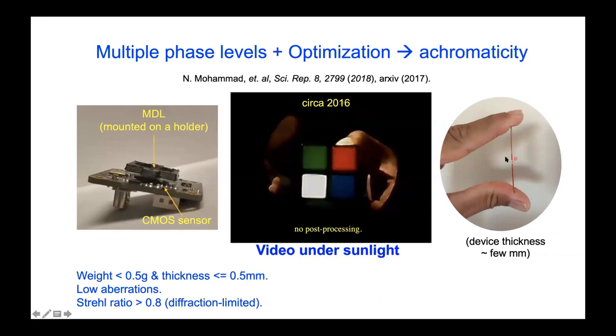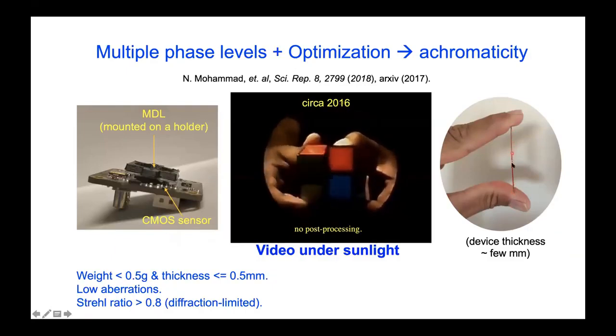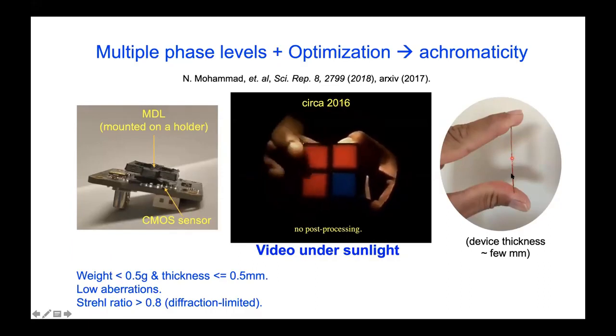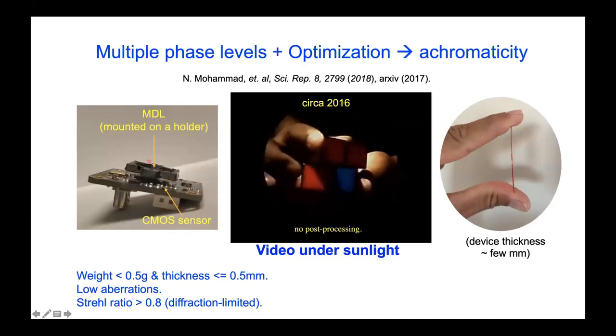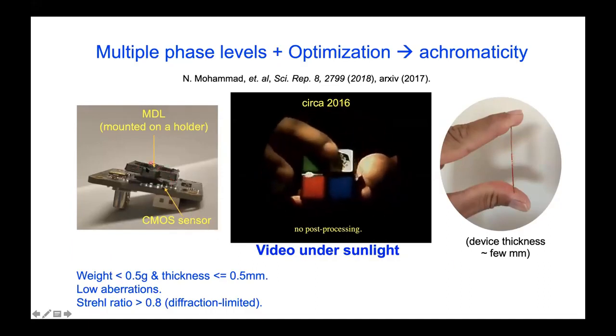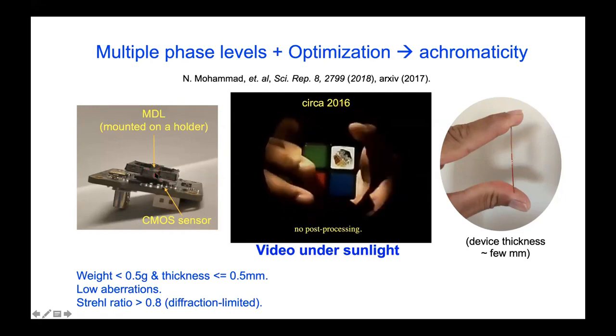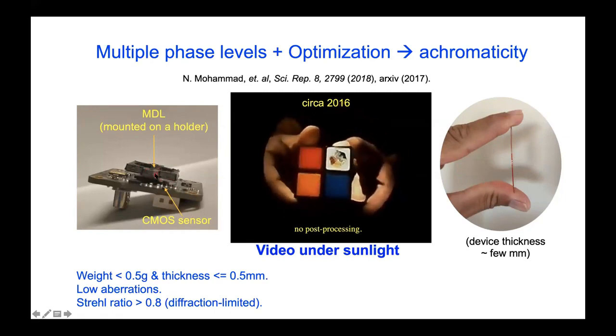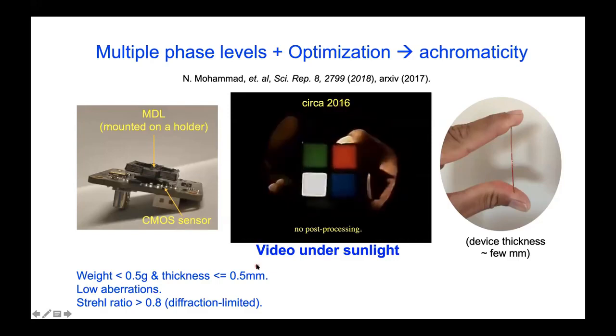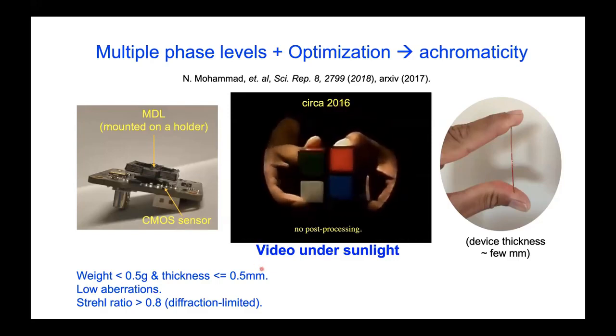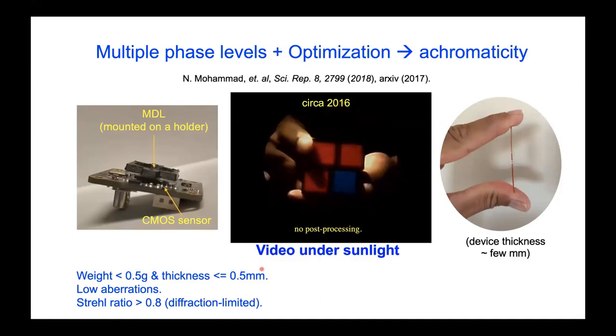So first of all, this is what our device looks like. We typically make them on a glass wafer. They're patterned with a polymer on top, typically photoresist, sometimes other materials. And we simply place the flat optic with a small spacer in front of a CMOS sensor. And we take images like this. So this is an example of a video under sunlight. It was just a raw image from about 5 years ago, where we can show pretty good achromatic performance.